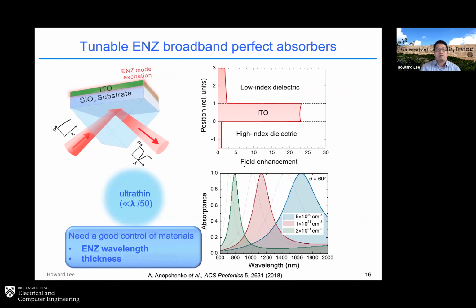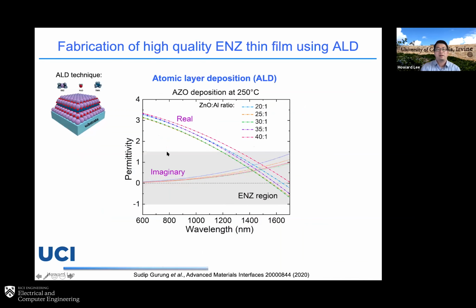And this is actually why we're trying to find a fabrication technique. We call this the atomic layer deposition technique, to make this ENZ material here. The good thing for this ALD technique is that you can make the material layer by layer in atomic layer thickness. At the same time, you can actually control the property of each layer differently. So that's why you can control the thickness really well, and at the same time the property really well on each layer.